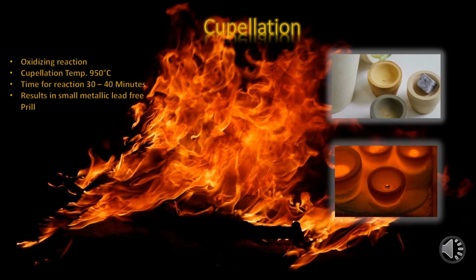The cupellation process is an oxidizing process for the partial refining of the lead button that is produced from the fusion process. Once the lead bead is broken from the slag material, it is hammered into a cube-like structure and placed into a muffle furnace at 950 degrees centigrade for 30 to 40 minutes. The oxidizing reaction produces molten lead oxide, which is absorbed by a cupel. This cupel is a porous pot used specifically for this purpose.